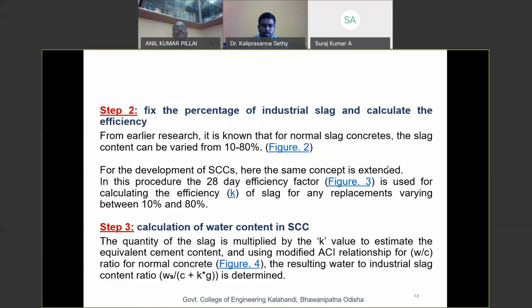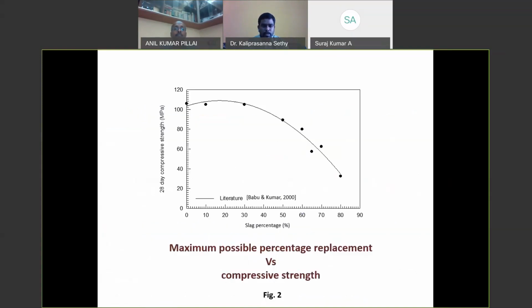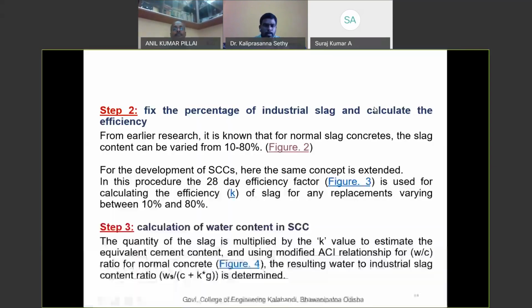From earlier research, it is known that for normal slag concretes, the slag content can be varied from 10 to 80%. Here is the diagram, given by Babu and Kumar in the year 2000. This graph is plotted between slag percentage and 28-day compressive strength, so the maximum possible percentage replacement can be found with compressive strength. If anybody wants to design an M60 concrete, from this curve you can find the corresponding slag percentage replacement, which will be around 60 to 65%. So according to this curve, we have set our slag replacement for the design purpose. And for the development of self-compacting concrete, the same concept is extended.